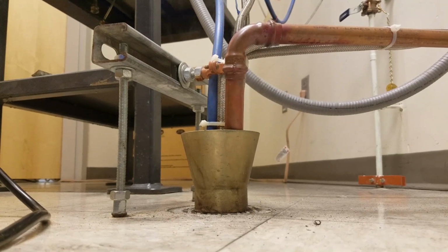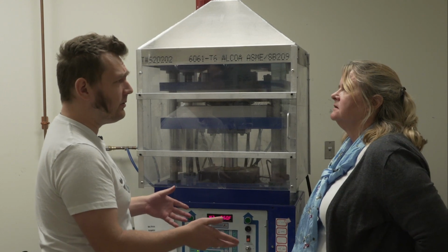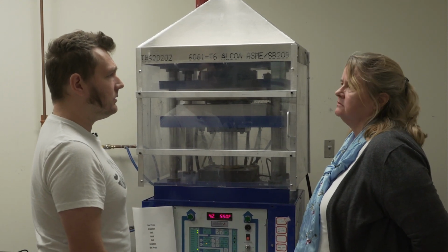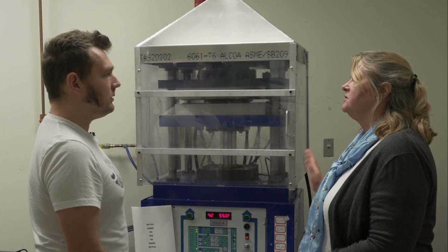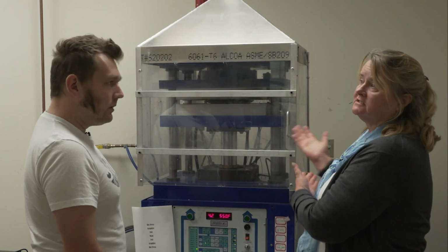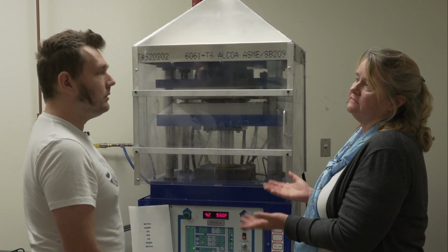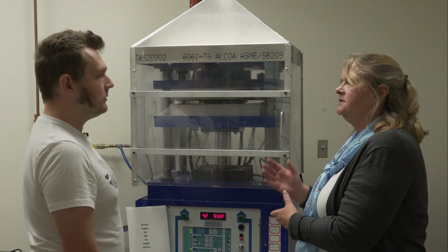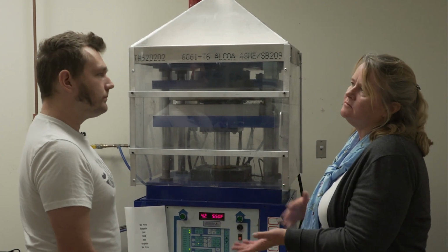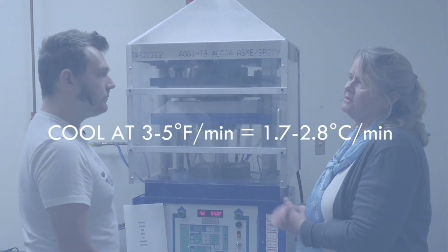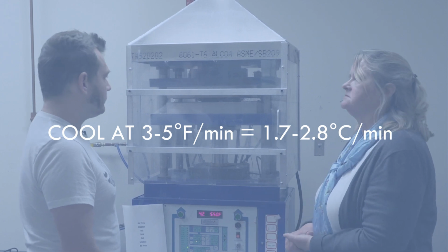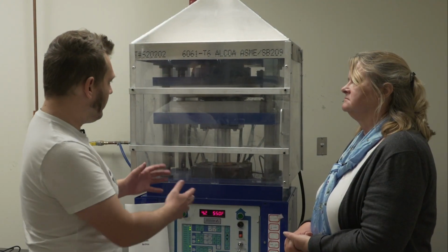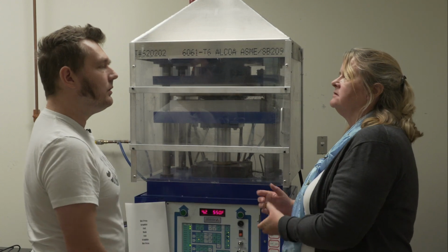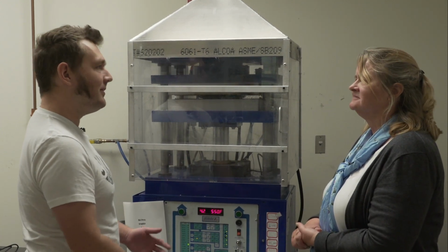Okay, got it. So will the aerogel crack if it's not cooled down slow enough? So if we have too high a cooling rate, it could crack. And essentially, we don't actually even need the hot press at this point. We could take it out and let it cool in the environment, but it's too hot to handle. So we leave it in there, which makes it easier. We cool at a rate somewhere between 3 and 5 degrees Fahrenheit per minute, and that results in good aerogels. Very interesting. So when will this be cool enough to handle? So about another 2 hours or so. Okay, great. We'll check back then.